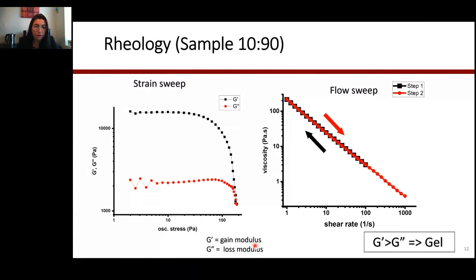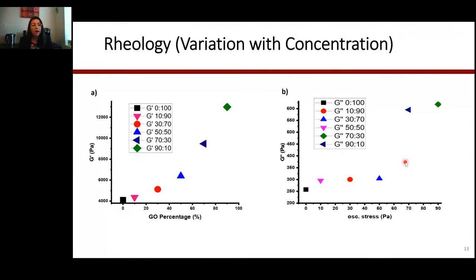From this graph of the flow sweep, the material went back to its original property almost every single time. It went almost to the same point it was before. It was really close to all of that. Could you see that viscoelasticity? After that, we had the rheology done for all the different concentrations of graphene and MoS2.